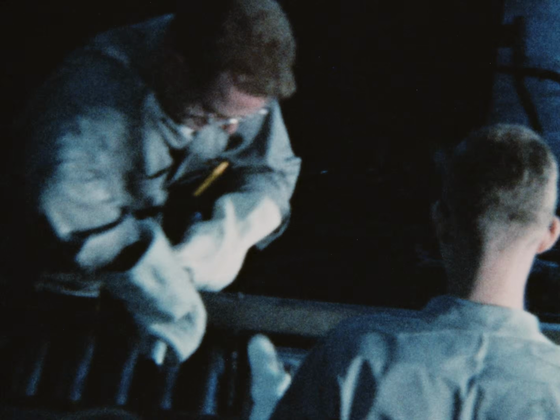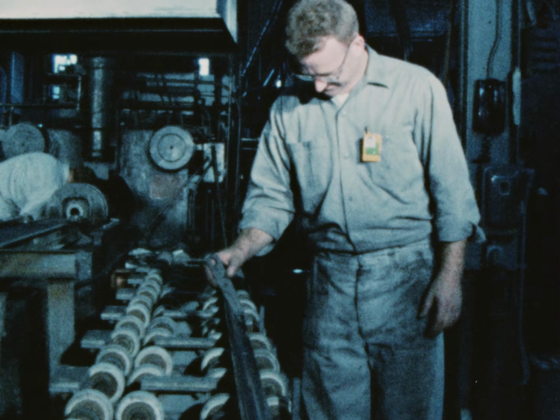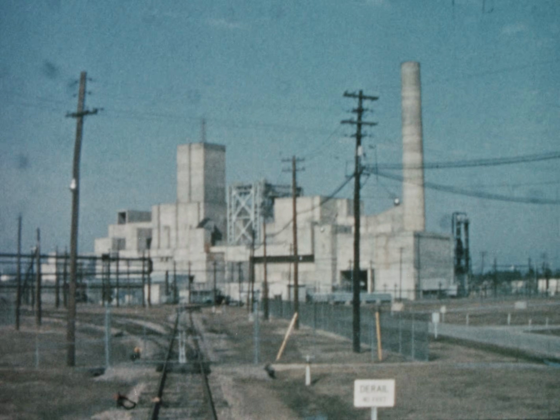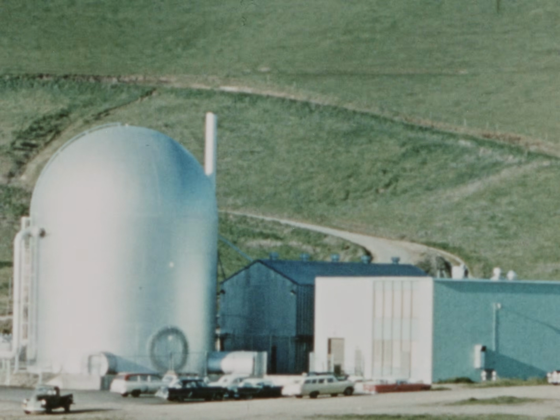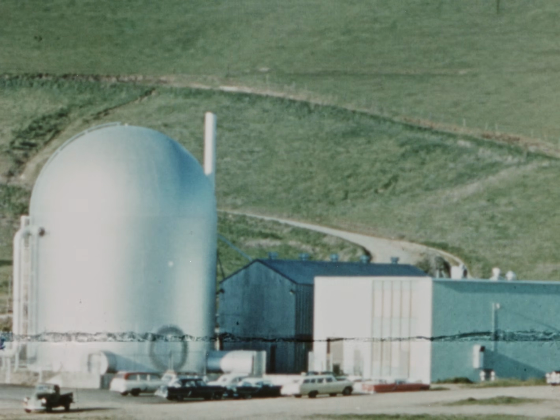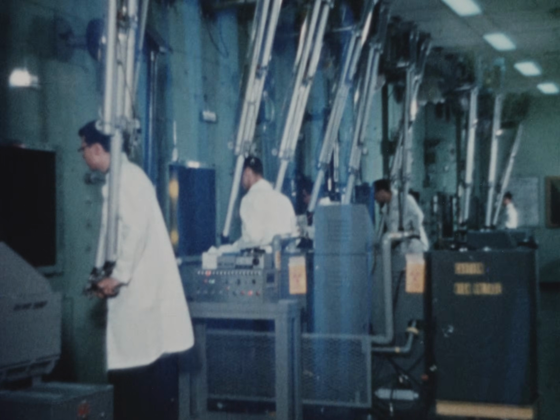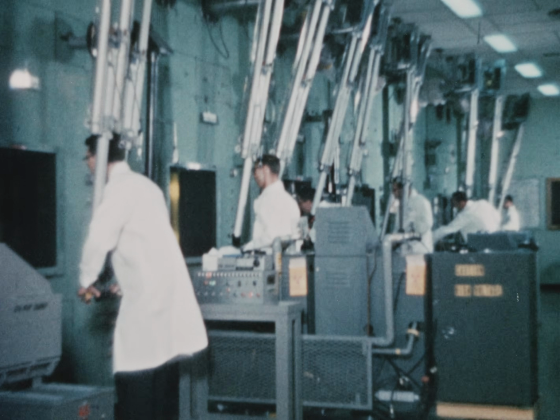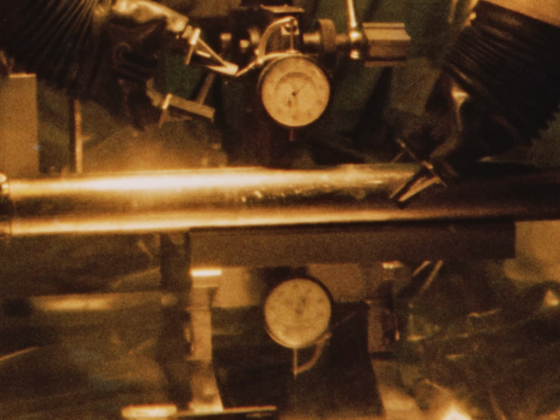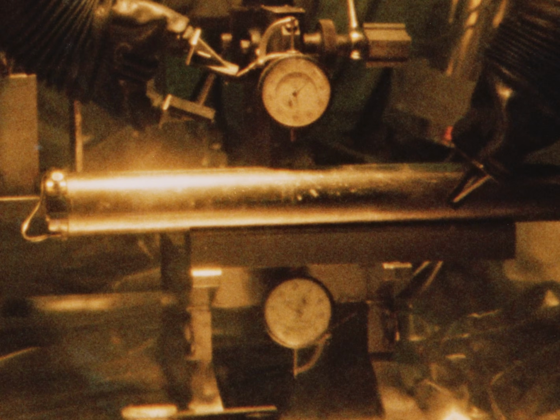Alloys of uranium, such as uranium zirconium and uranium molybdenum, were studied to improve dimensional stability under irradiation and increase corrosion resistance. Samples of these fuel elements were irradiated in the Savannah River production reactors, the Vallecitos boiling water reactor, and the E20 loop of the NRU at Chalk River, Canada. Post-irradiation examination of fuels in high-level caves was performed at Savannah River to guide development of the fabrication process.